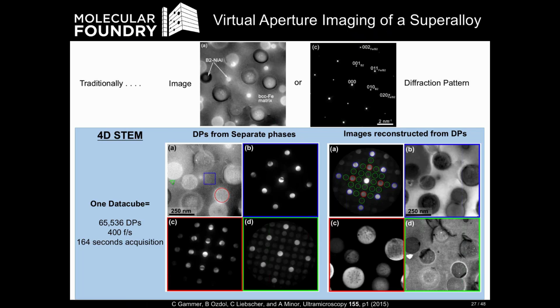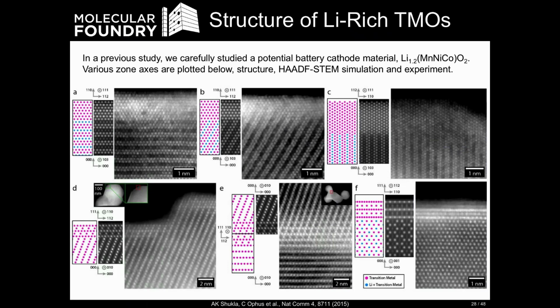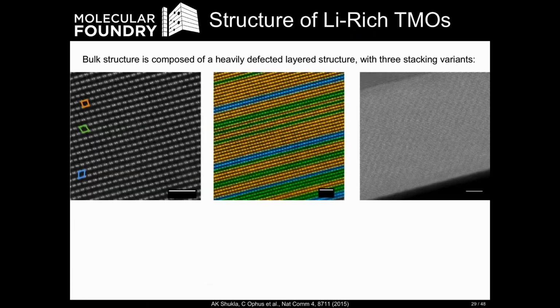Another example I'm going to show for this virtual imaging is lithium-rich transition metal oxides. This is a conventional study we did a couple of years ago showing annular dark field images. I just want to show that these are structurally very rich and complicated materials. This is the same sample, but along different zone axes. You can see there's a different surface layer and a lot of stacking defects. In this material in particular, these images don't cleanly show it, but it has a lot of random stacking defects. This particular zone shows it really nicely.